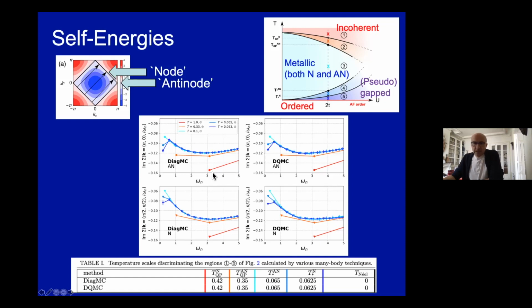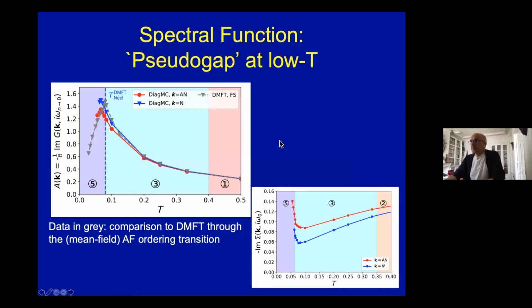And so one can claim that within this range of temperature, these methods allow for a complete computational solution of the problem, and in particular, determination of the various temperature scales that separate these different regimes. You see, however, that one cannot go to arbitrarily low temperature, and basically inverse temperature beta equals 16 is more or less what can be reached these days with these methods.